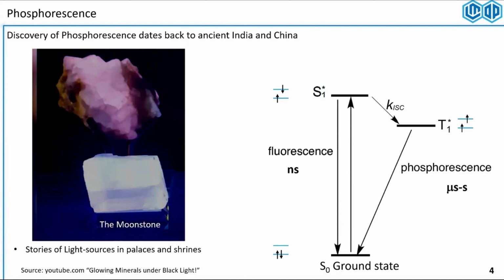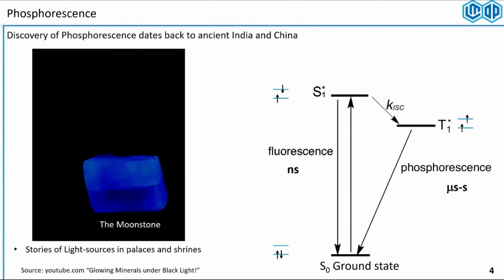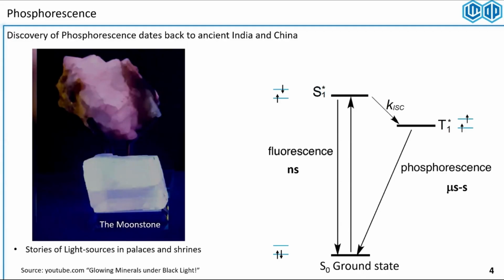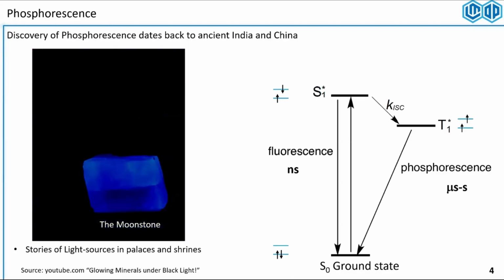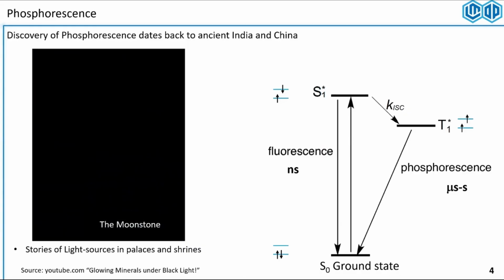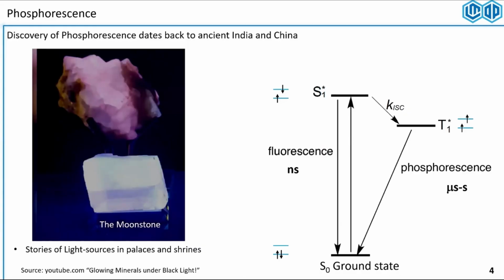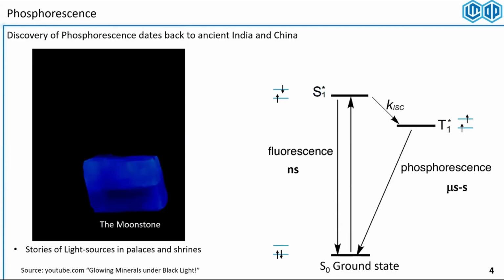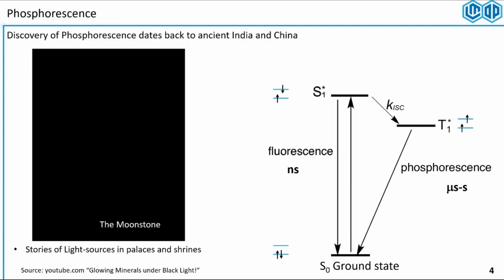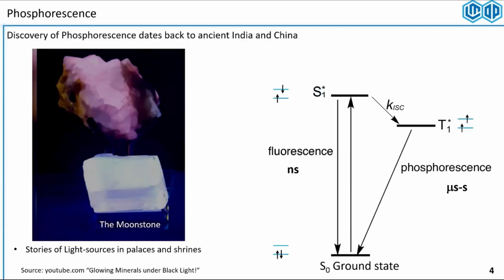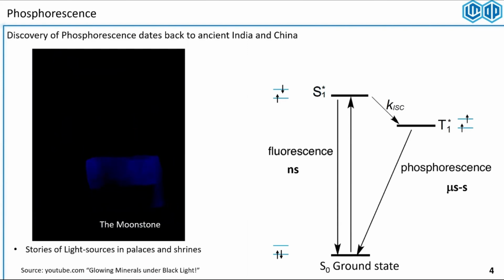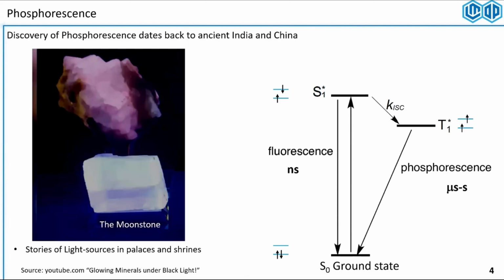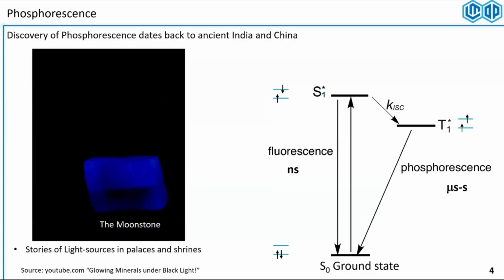from the ground state, it goes through a singlet excited state, the same sort of preserved spin. And if the singlet excited state emits back to the ground state radiatively, you generate fluorescent light, normally spontaneously in nanosecond lifetime. But if it goes through an intersystem crossing, it will flip the spin of one of these electrons essentially to generate a triplet excited state. Now this triplet excited state is a metastable species, and that will not decay back to the ground state. It will stay for a long time until it does another intersystem crossing to the ground state, giving this afterglow essentially as the phosphorescence.